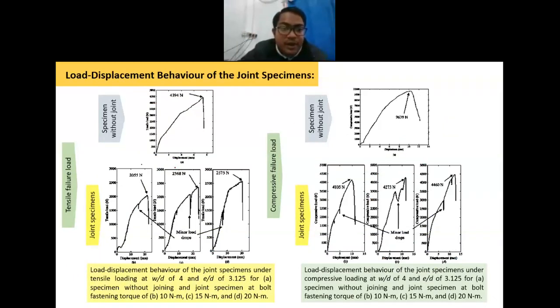So here you can see this is the specimen without joint, having the maximum tensile load of 4,394 newton. But for the joint specimen, it is almost 50% reduction in the tensile load. So 2,055 newton, 2,348 newton, 2,375 newton. These three graphs are for the three bolt fastening torques of 10 newton meter, 15 newton meter, and 20 newton meter. And what we have observed is that if I increase the bolt fastening torque, it gives me better joint strength in terms of maximum tensile failure load.